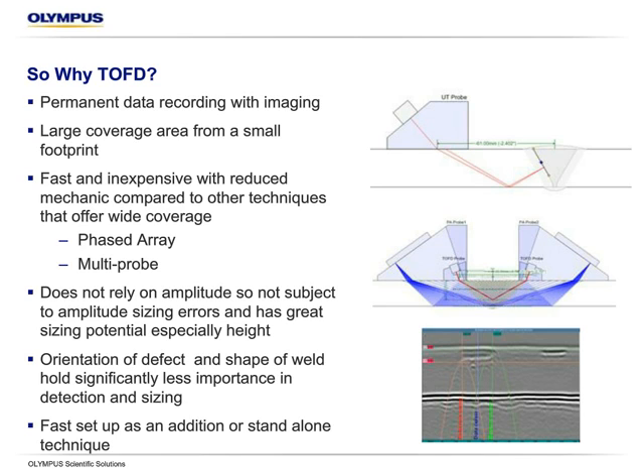Very fast and inexpensive. It's very fast because we're only using one beam. In contrast to phased array, for a typical 1/2 inch, 3/4, 1 inch weld, we might have 70 different beams to get full coverage from both sides of the weld, where in that thickness zone, TOFD might be able to do it with some very small dead zones, but pretty much 100% coverage with just one beam. So that means we can move at a magnitude 70 times faster in a typical application than a phased array.